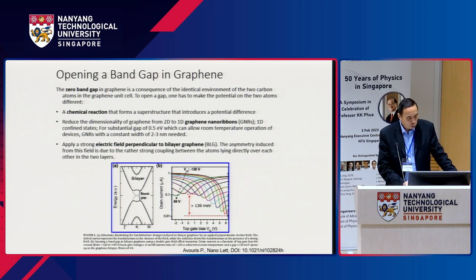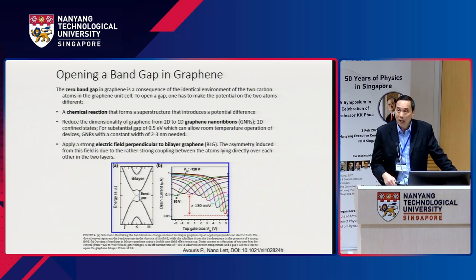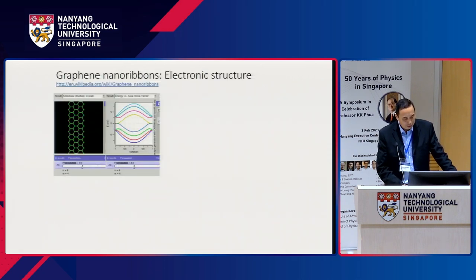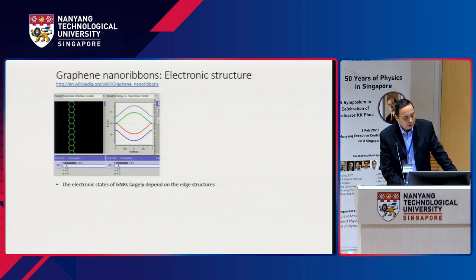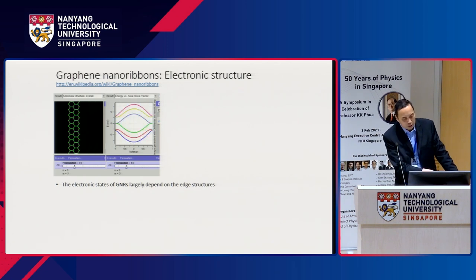And of course, there's also a way of applying an electric field to bilayer graphene to cause such asymmetry on the surface. So for a while, we did look at some of the first two ways of creating a band gap. This was just some simulations showing that even with graphene nanoribbons, depending on how they're terminated, zigzag or armchair, the electronic states depend on this edge structure. So you see it's all metallic for these zigzag nanoribbons.